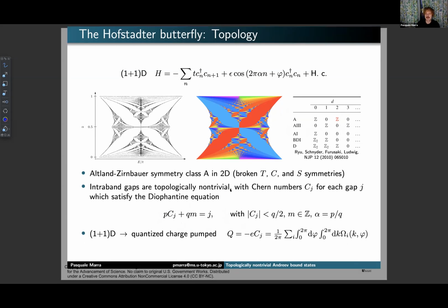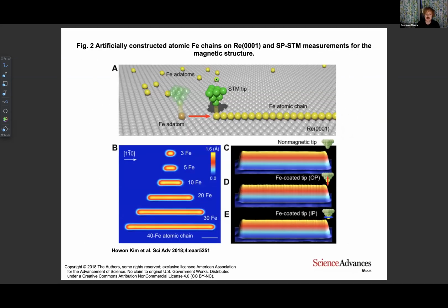This is not only theoretical, because one can realize this system, and it has been realized in a similar system. If one has iron atoms on the surface of a superconductor, one can have an amplitude modulated magnetic field, which has been measured in this system.